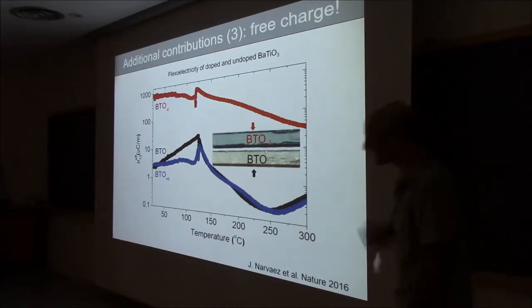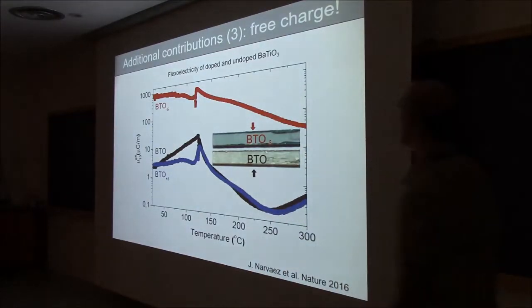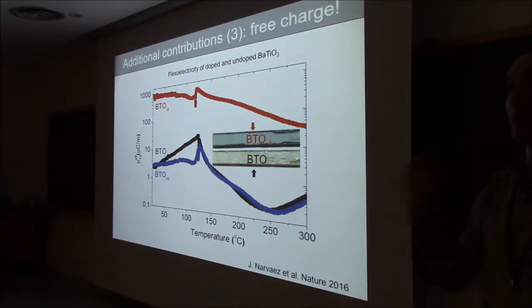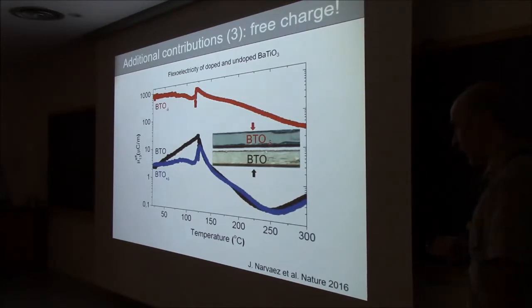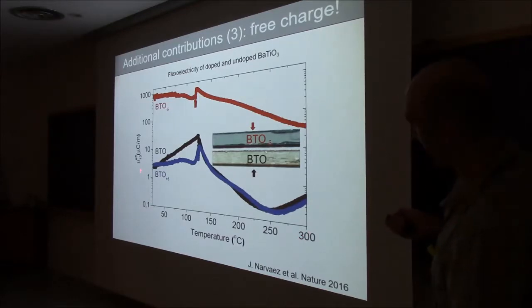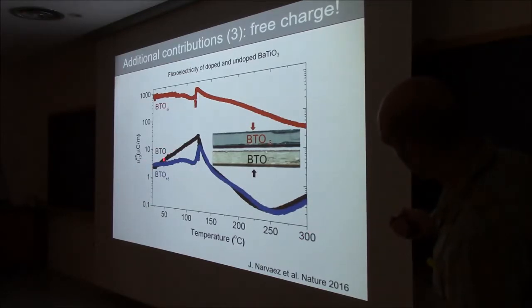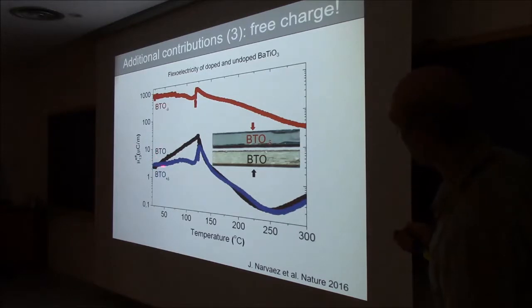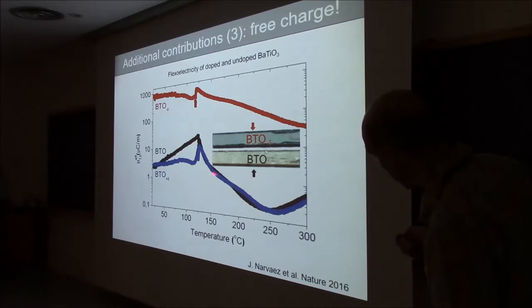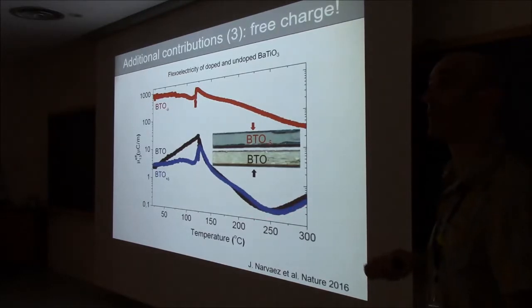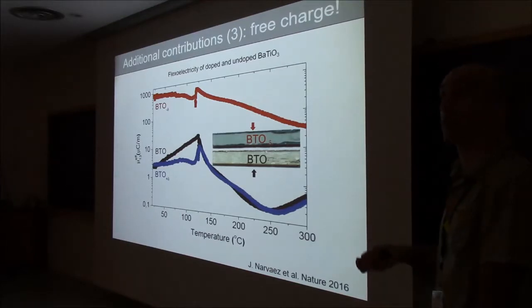Okay, and there's another additional contribution to flexoelectricity which you can have in semiconductors, and that contribution comes from free charge. If you look at barium titanate, the flexoelectric coefficient as a function of temperature more or less follows the dielectric constant. You have a bump here, this has to do with polar nanoregions, here you're more or less in the intrinsic regime, and then it starts to go up. And this starting to go up very much coincides with an increase in leakage in our sample.